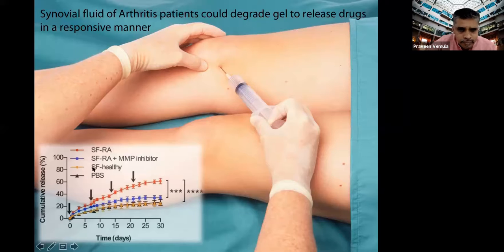As you can see, this yellow line, where the gels were exposed to the synovial fluid taken from the healthy volunteers, the release wasn't great, because the release is similar to what we observed in the PBS, right? That means your synovial fluid is not really promoting any additional release. Whereas when the synovial fluid taken from the arthritis patients was exposed to gels, you can see the release of the drug. Whenever you give fresh pulses, it keeps increasing the release of the drug, which is clearly suggesting that the inflammation present in the synovial fluid in arthritis patients can trigger the release of the drug in an on-demand manner. Whereas if there is no inflammation, this might not release the drug, right?